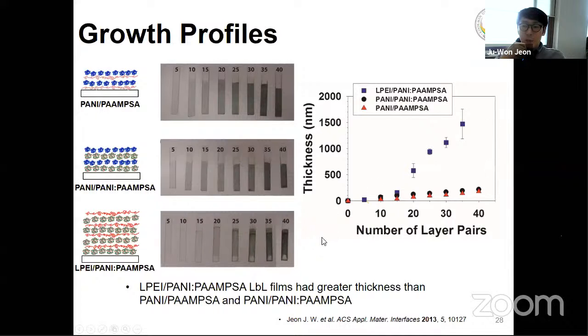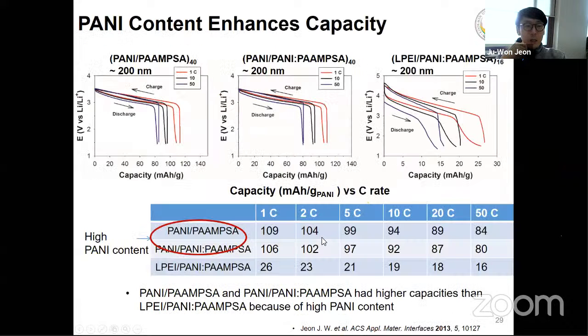And these are the growth profiles of the LBL films. And the PANI/PAAMPSA has the highest capacity, higher than the LPEI/PANI:PAAMPSA, because of the high conductive polyaniline content. But the LPEI/PANI:PAAMPSA has very low capacity.